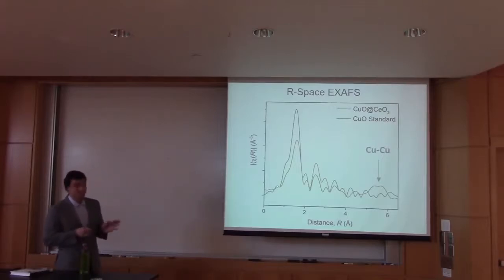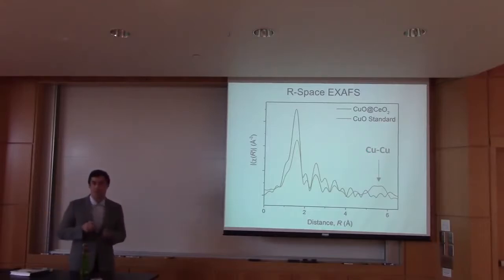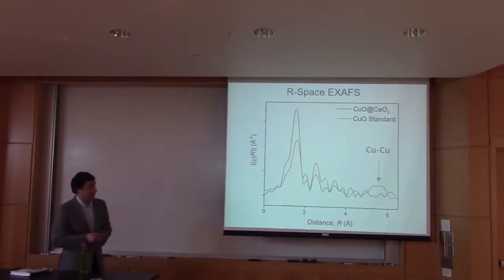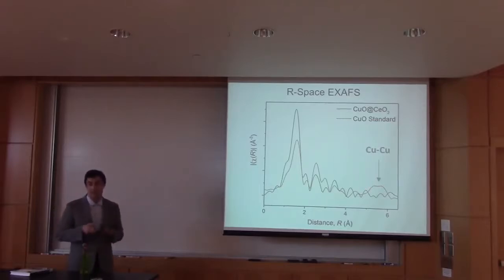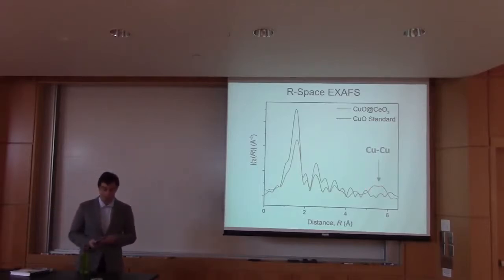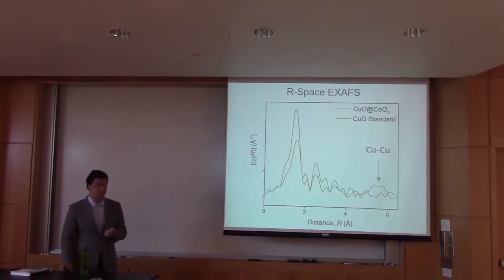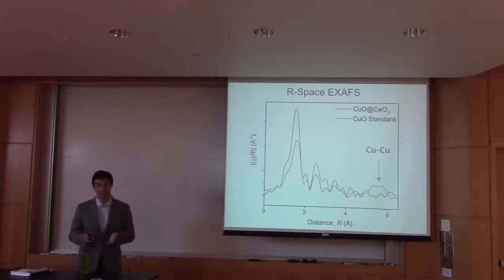There's two important peaks in this plot, and I want to draw your attention to the most important one, which is this copper-copper scattering distance. And what we see here for the standard is it's relatively pronounced compared to our actual catalyst sample. And what we take this to mean is in our catalyst we have a smaller copper oxide domain compared to this standard, which is good, and it means what we have done so far has been successful in this MOF templating process, and we should have a more efficient catalyst.